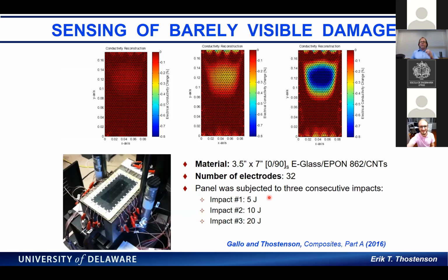So this is just another example. We wanted to say, well, can we really sense this barely visible impact damage? And I think, what impact damage is, the example often used is if you have an aircraft wing and you drop a hammer on it, you can't see the damage, but is there damage there? And so what we did is we did some low velocity impact. We took our composite and we put it in our impact tower. In the photograph you see here, this is our composite laminate, and you see the electrodes all the way around the boundary. This is a little bit tedious to apply, but we can actually integrate this into a printed circuit board, and we have.